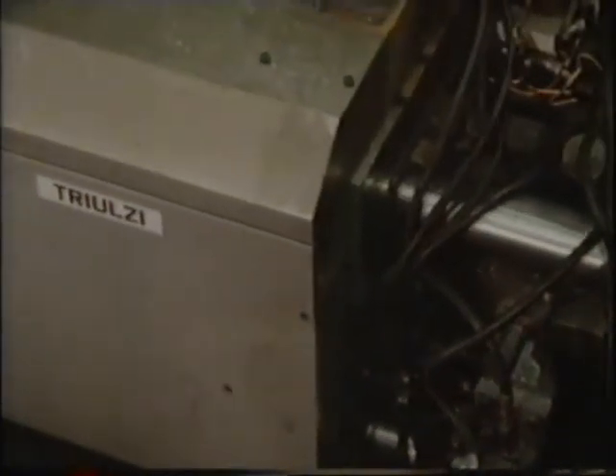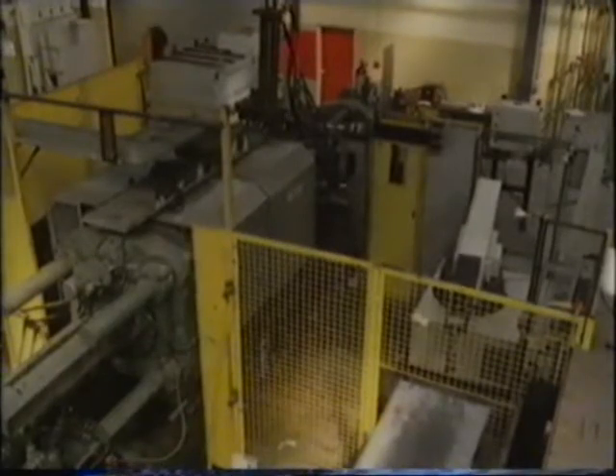One method is to inject the metal under a high pressure into a water-cooled die. The technique is known as high-pressure die casting. The metal is injected into the die with a plunger, which can exert a pressure of up to 14,000 pounds per square inch. The die itself is mounted between the two plates of a horizontal press. The press has to lock tight so that it can stand up to the high pressures exerted, and it'll vary according to the size of the casting.